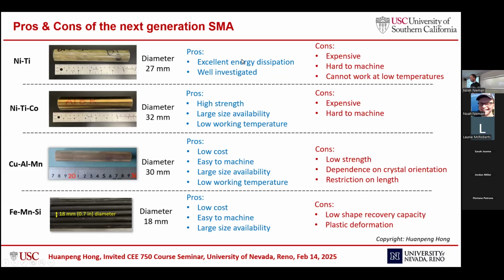The pros of this material are that it has excellent energy dissipation and it is well studied. And the cons of this material are that it is expensive and it is hard to machine. Later, I will introduce some machinabilities of this material. We can see the details of how hard it is to machine this material. And also this material cannot work at low temperature, specifically lower than 0 Celsius.